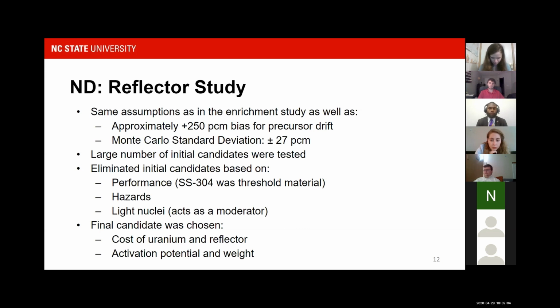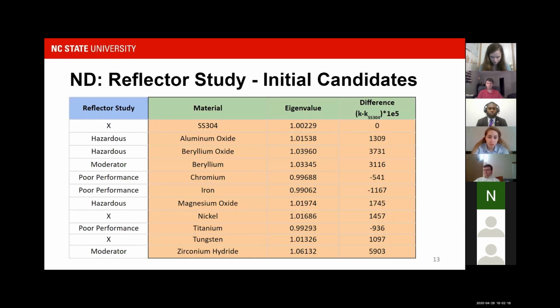The final candidate was ultimately chosen to minimize the cost of the uranium and reflector, balanced with the activation potential of the reflective material and the weight. So here is a summary of our results for our initial study. We see that 3 of the candidates, denoted with an X next to them, move on to the final, while the rest of them are eliminated based upon the reasons I gave on the left. We see quite a few different potential candidates, but because of the hazards associated with them or because they moderate the spectrum, we eliminated them.